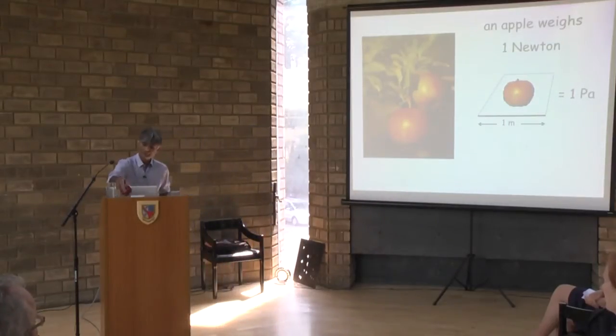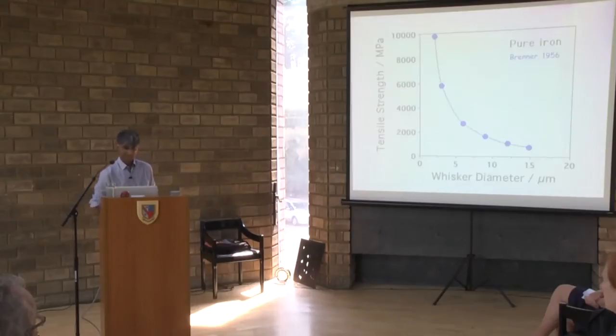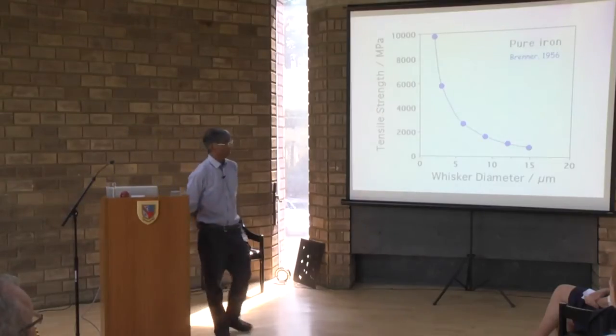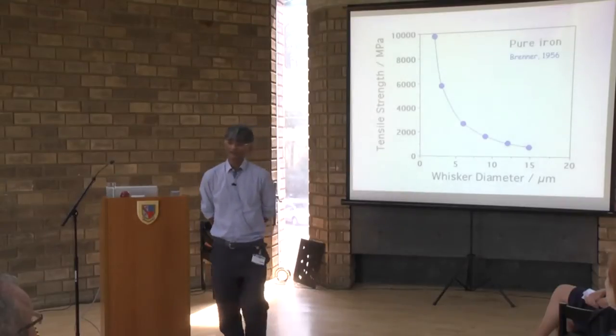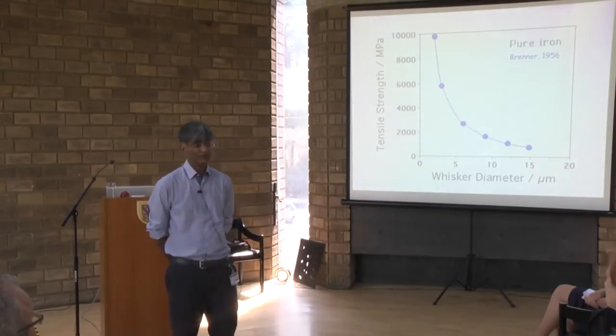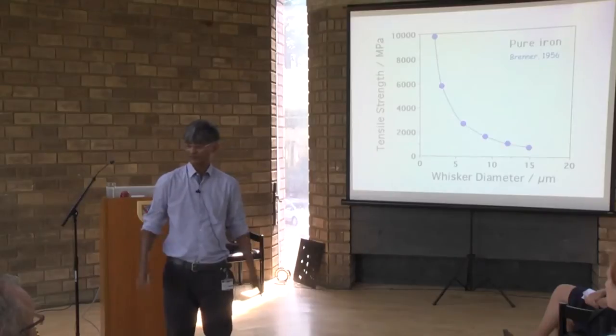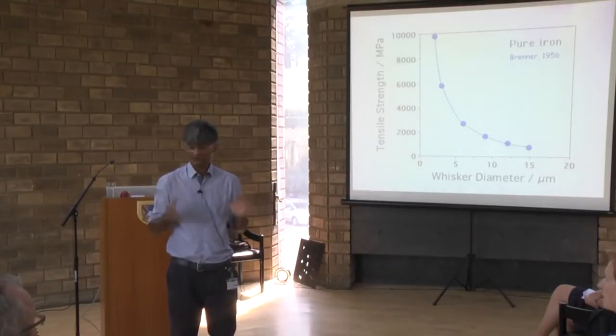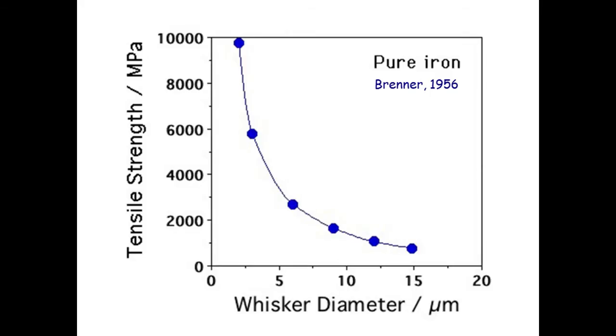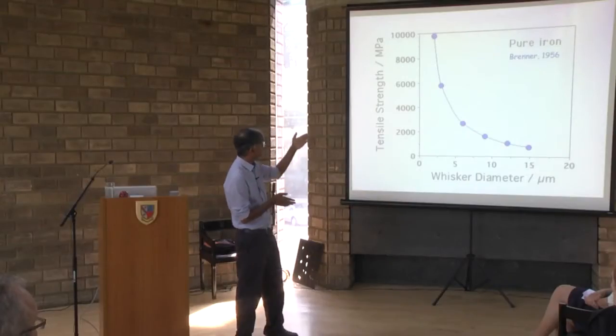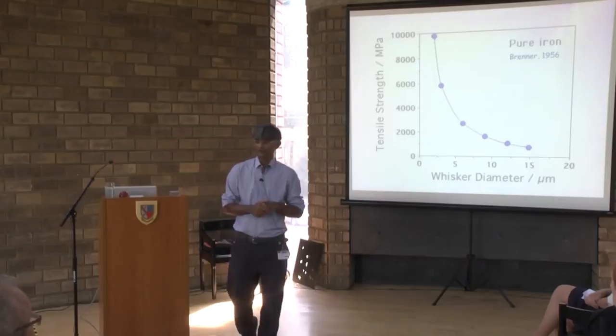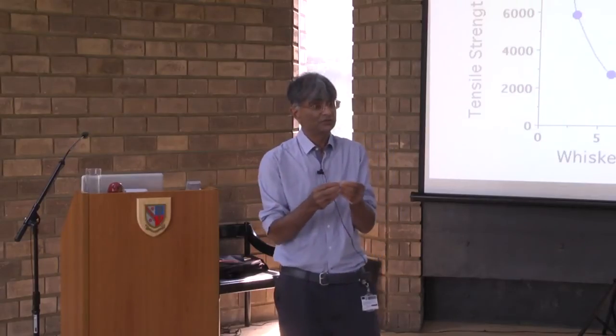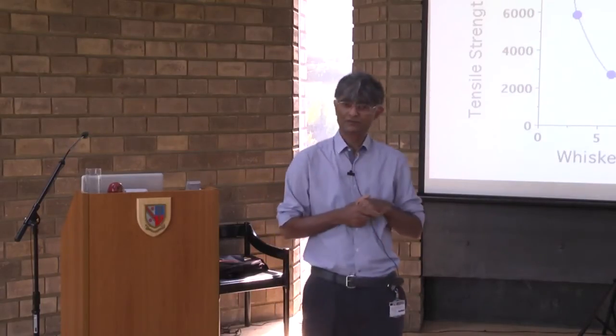So back in 1956, we could actually make iron with a strength of 10 gigapascal. That means 10 billion apples on 1 square meter. But look at the size scale there. We are talking about a particle of iron which is about 2 millionths of a meter in size. And you can see that the strength collapses as soon as I scale that up to a larger size of 20 millionths of a meter.